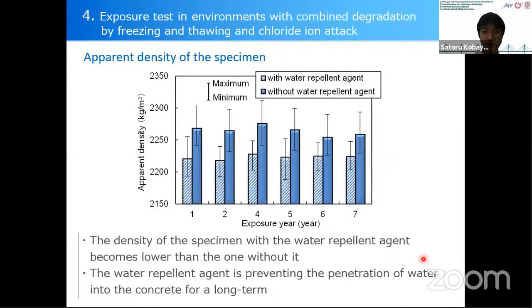This is the result of the density of the specimen. The results are completely different depending on whether the specimens are coated by the water repellent agent or not. The diagonal line like this is with water repellent agent. Blue is without water repellent agent. It was confirmed that the density of the specimen with the water repellent agent becomes lower than the one without it, because the water repellent agent can prevent water penetration. From the result, it's obvious that the water repellent agent is preventing the penetration of water into the concrete for a long time. Horizontal is the exposure year. This is 7 years after the exposure test.